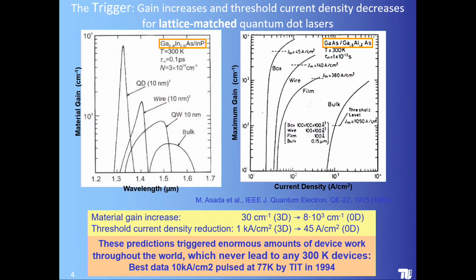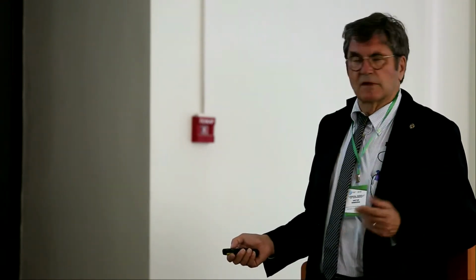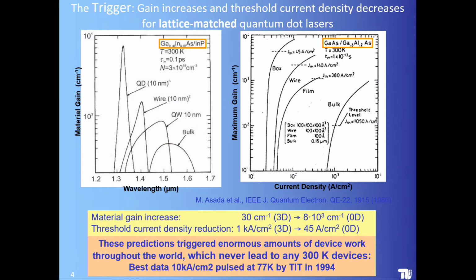From here on you might have, if you're really good, and that is what we have with quantum dot lasers, 100% slope efficiency. So these are very important predictions in the 80s, almost 40 years ago. And they triggered enormous amounts of device work all over the world, which never led to any 300 Kelvin device. The best device, which was published 8 years later in 1994 from the same institute, was a laser pulsed at 77 K, that was liquid nitrogen temperature, having a threshold current density of 10 kiloamps per square centimeter. That was just enough to take the IV characteristic, and then it died. So that was very disappointing because many companies had invested a lot of money.